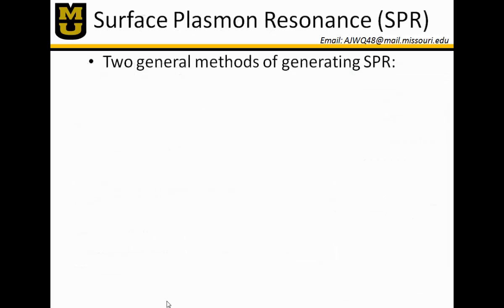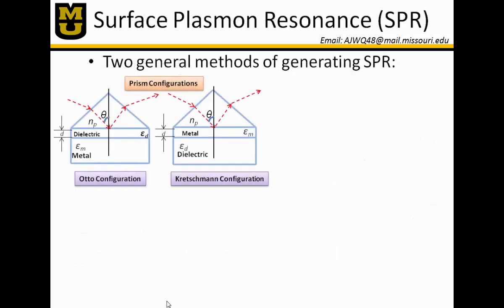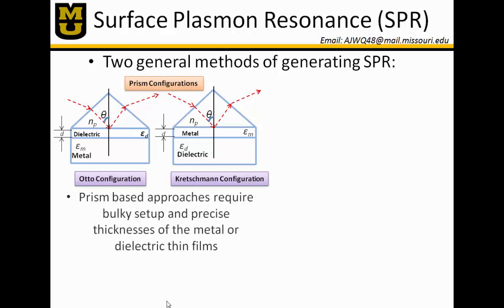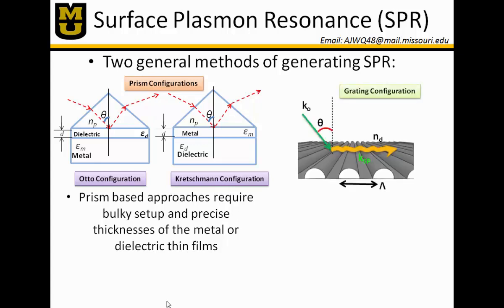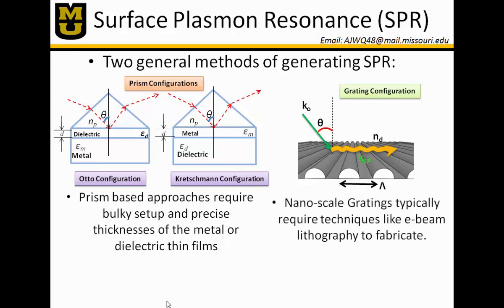So if we look in literature, there are two general methods of generating SPR. There's first your plasmon or prism-based configurations, in which you increase the momentum of the photon that travels through the prism, and it forms SPR at this dielectric metal interface. Now, unfortunately, this process typically requires bulky and expensive optical setups. The other method that they can use is grating configuration. So by using the diffraction of a photon off of this grating pattern, you can gain enough momentum to excite surface plasmon resonance. But again, there is a downside to this. The formation of these nanoscale gratings often requires E-beam lithography or interference lithography, which can be very expensive.